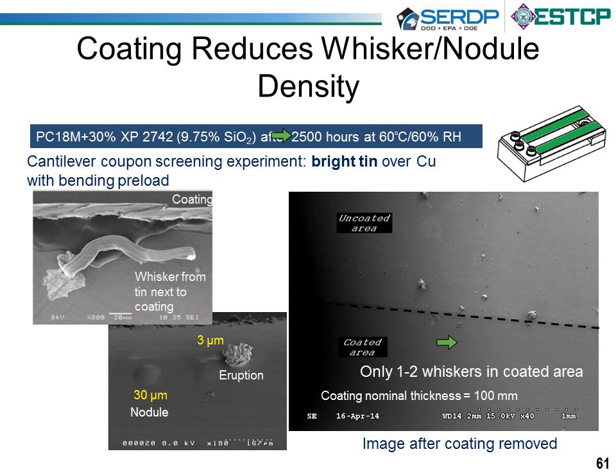One interesting thing is that the coating itself, in areas where it was thick, had very little whisker nodule growth, very little. And where it started getting a little thinner, as it started tapering off an edge, this is the uncoated area, and here's the coated area. The uncoated area grew whiskers right next to the coating.